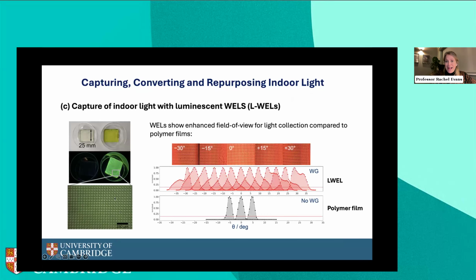So how does this lead then to an enhanced field of view for collection? What we do is we compare the L-well templated film with a bulk polymer film with no channels in it whatsoever. And we shine light on the top surface at different angles of incidence. And then we measure the light that's collected below the sample. And what we see is when we have the waveguides, we're able to collect light at lots of different angles of incidence, from -30 to 30 degrees. But when there are no light guides present, we only manage to collect light when it's directly incident on the top surface at 0 degrees.